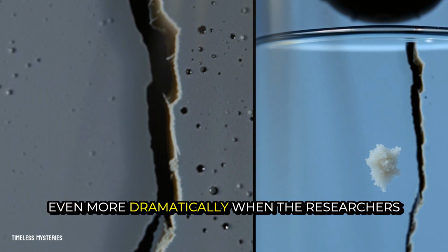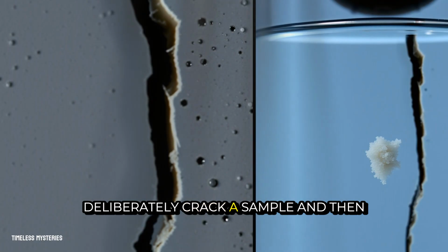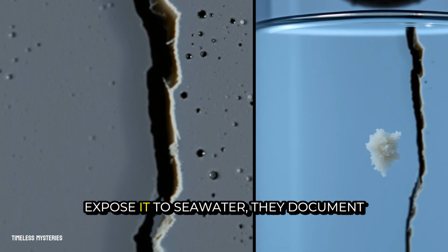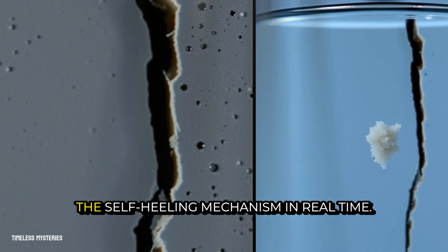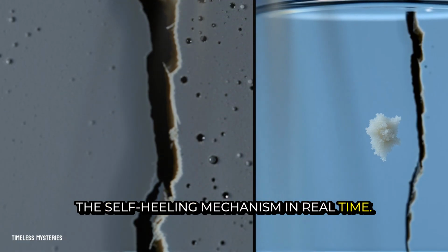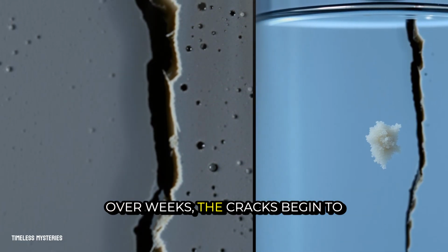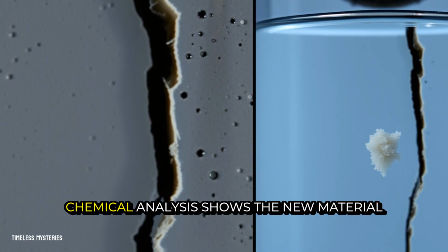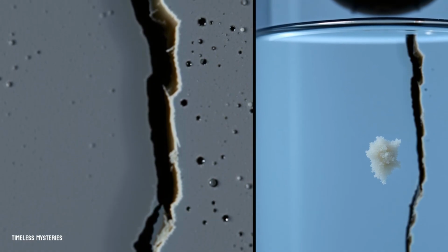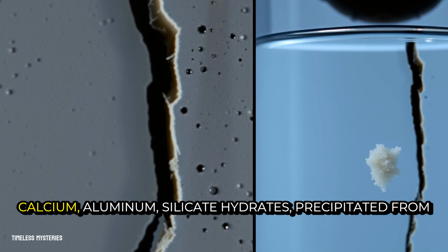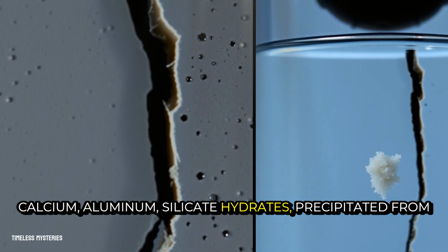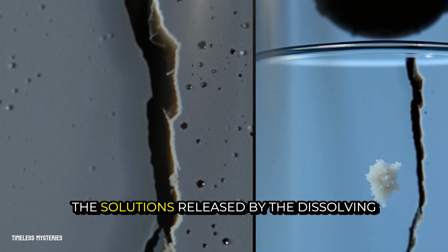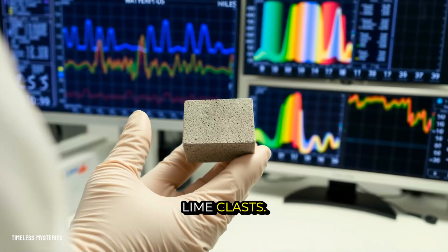Even more dramatically, when the researchers deliberately crack a sample and then expose it to seawater, they document the self-healing mechanism in real time. Over weeks, the cracks begin to fill. Chemical analysis shows the new material sealing the gap is rich in calcium aluminum silicate hydrates, precipitated from the solutions released by the dissolving lime clast.